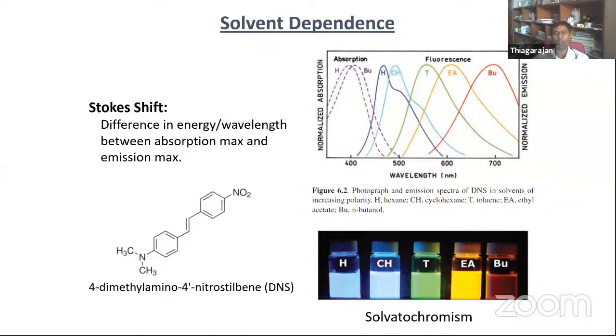We can see the very well-known probe DNS, 4-dimethylamino-4'-nitrostilbene. This is a well-known probe because it shifts enormously with the solvent polarity, from 400 to 800 nanometers, a very large shift region. Depending upon the solvent, we can tune the emission of the probe. We can have it blue, green, yellow, or red from the same probe, because we can stabilize the charge transfer in different patterns.